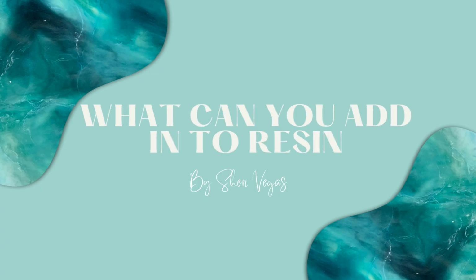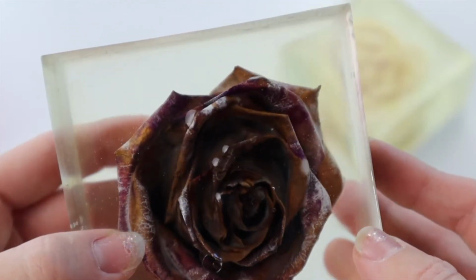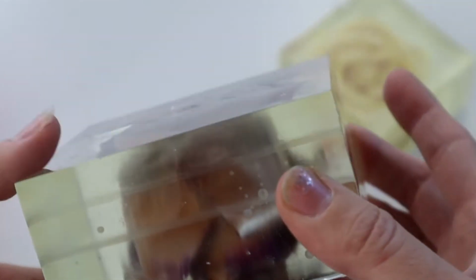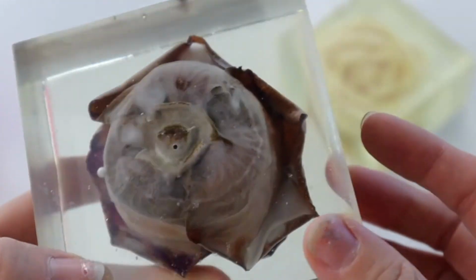So what can you add into resin? Because I've talked a lot about adding items into resin and doing clear castings. And basically you can add any items as long as they're dry. So as long as they don't contain moisture. So if you want to put flowers in, you cannot add fresh flowers in. If you add fresh flowers into resin, they will look good for like maybe a few days, a week, look really amazing, but the moisture gets trapped inside the resin and has nowhere to go, so it starts to rot the flowers and you'll end up with just black flowers in your resin and it looks terrible. So any item you add in needs to be a dry item. It cannot have moisture because it will get trapped in there.